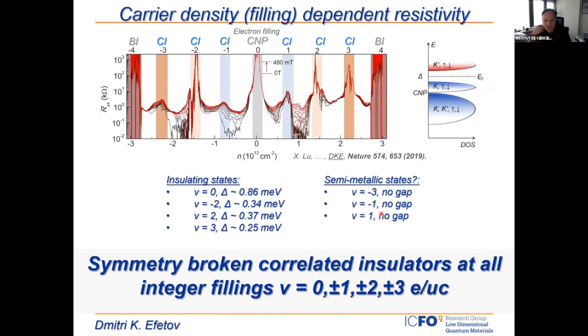So we just measure resistance as a function of carrier density. We sweep the Fermi energy from a completely empty Moiré band through it until we completely fill it. As you see, the carrier density changes by orders of magnitude if we do so. First of all, when we start in this lower energy gap, we find this robust insulating state.